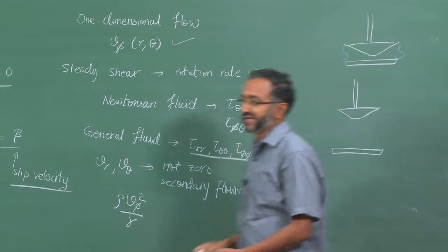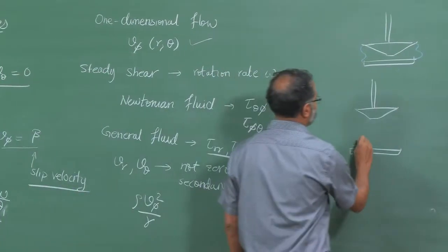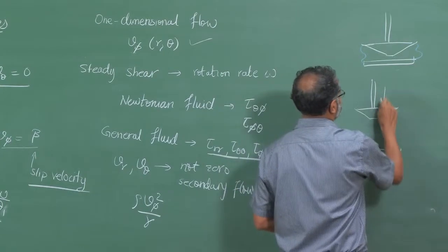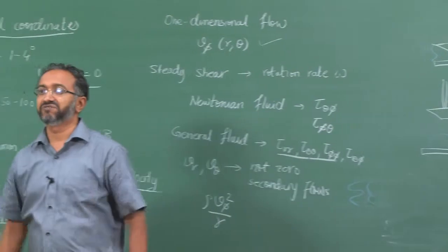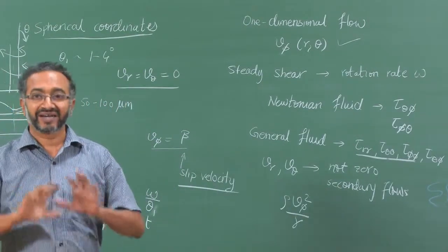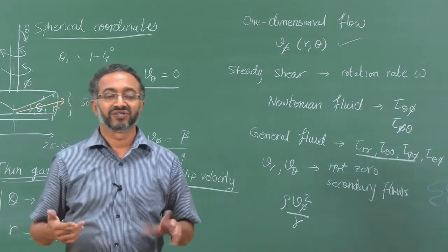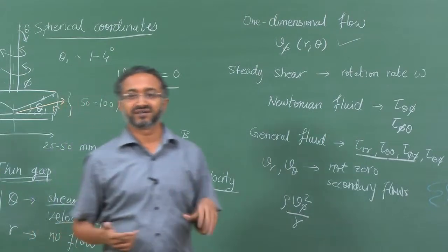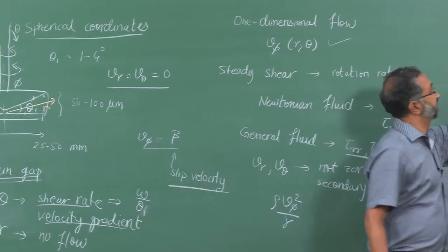So the fluid will be only kept on the bottom plate, and then this will be lowered. So I will just do this and then lower this. Depending on how I lower, the interface will be formed. So if the results are dependent on how I lower, then again I am not examining material behavior, but I am examining something else.